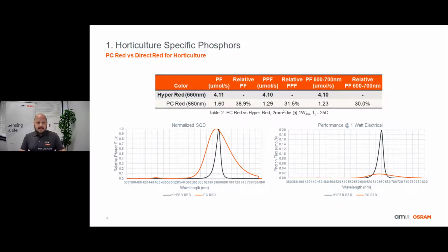So the SQD that we see on the bottom left shows the normalized photon flux output of both the phosphor-converted and a direct-emitting red LED. So as you can see, the result of phosphor conversion creates a relatively broad red spectrum. The centroid wavelength of this is around 660 nanometers. However, about 20% of the photons are actually extended out past the PAR range and into far red. This would further reduce the LED's photosynthetic photon efficiency value.